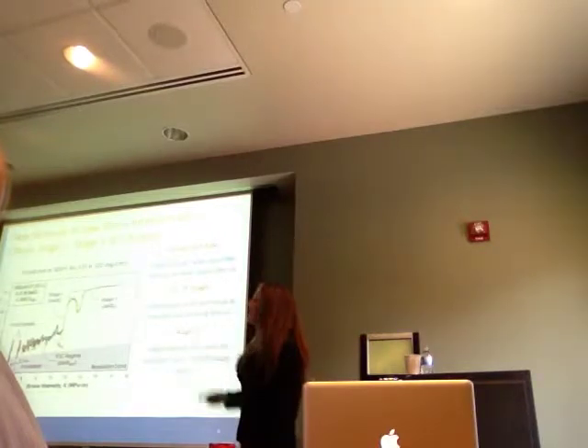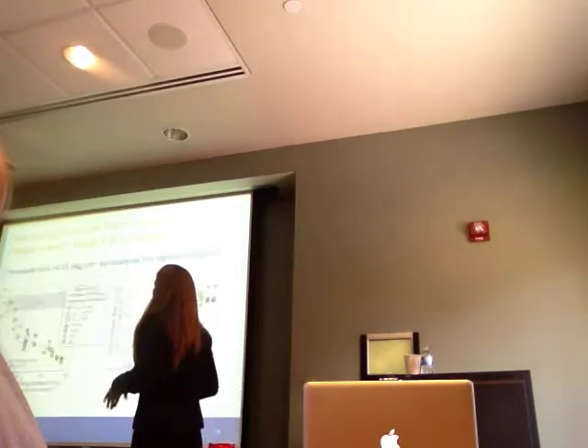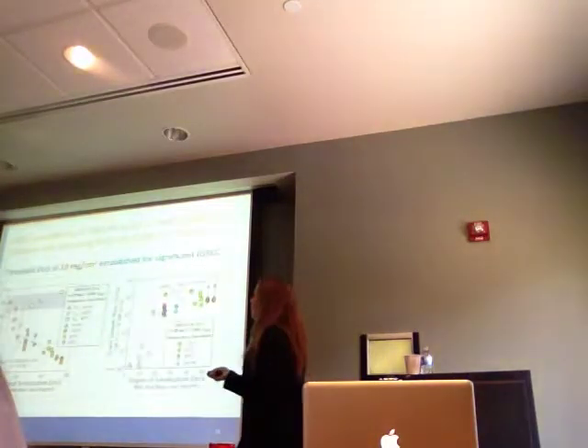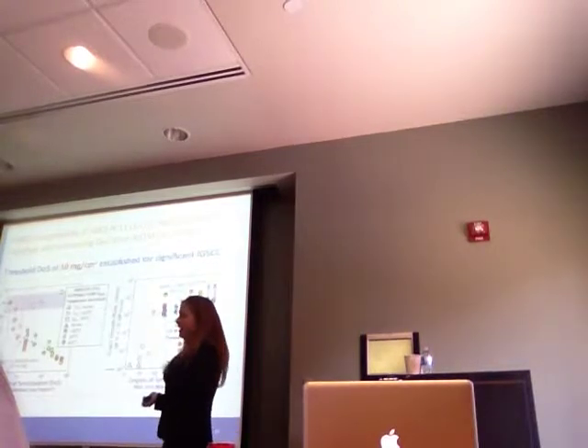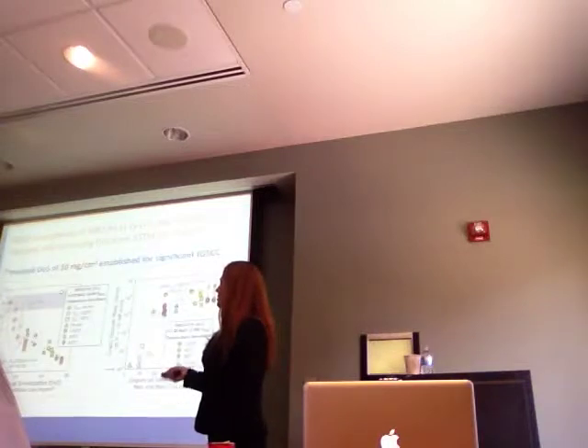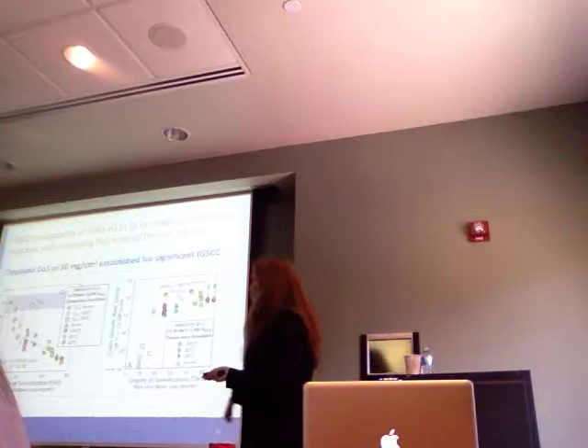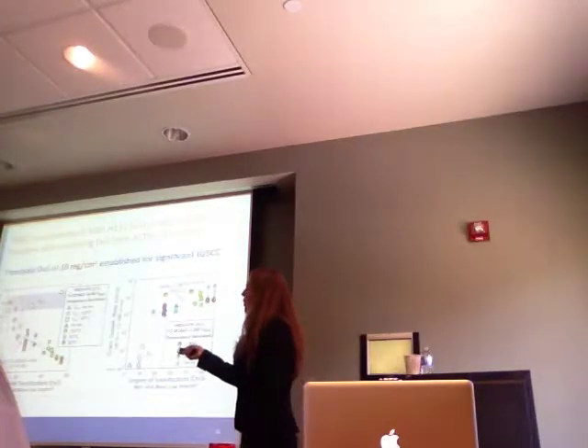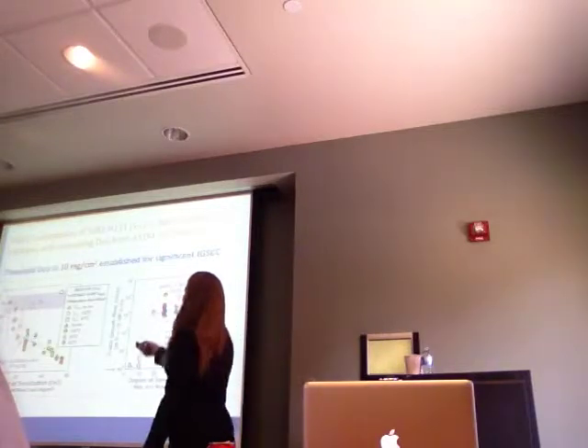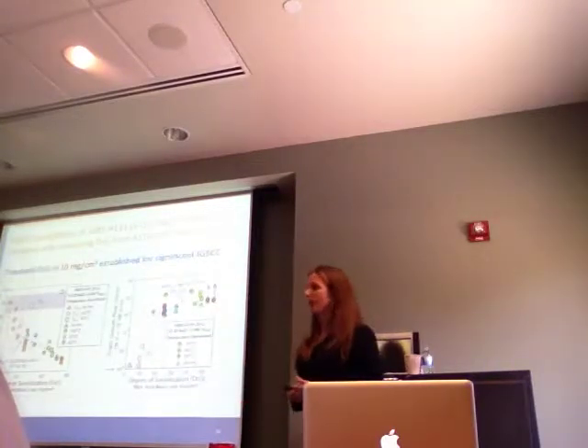So if you remember threshold stress intensity and stage 2 crack growth rates, I plotted both for all of the sensitizations that I looked at. And you can see on the left here, when you have a very low degree of sensitization, very low either temperatures, times, or mass loss measurements, your threshold stress intensity is within the region of your fracture toughness. So it's as if you're not even in sodium chloride, you're breaking as if you were in air.